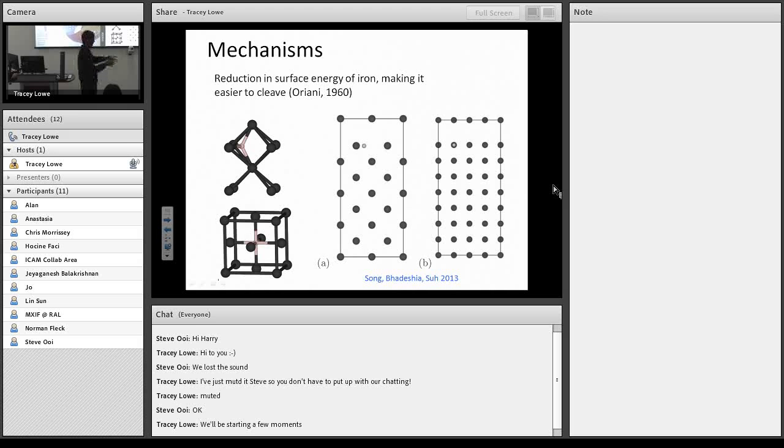So what you do is you take a number of atoms in your computer, you place a hydrogen atom inside that cluster, and then you have to cleave it. Now, how do we cleave this? Well, the spacing between this layer and this layer is much larger than the spacing here, and you increase that vacuum space until it doesn't make much of a difference to the total energy of the system. That means you've created a cleavage of material.